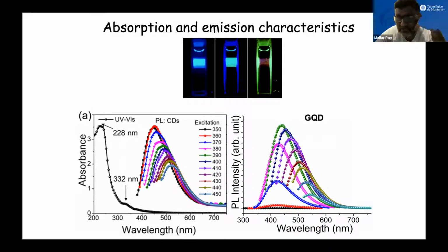Now, this kind of feature was very well known for the graphene dots. And in fact, it's difficult to make graphene dots, small pieces of graphene in a colloidal suspension. To our amazement, when we compared the optical properties of the graphene quantum dots and the amorphous quantum dots, we saw a striking similarity between them. These graphene quantum dots, which are much more difficult to make, more exotic, and these amorphous clusters of carbon dots, their photoluminescent emission spectrum, their UV visible absorption spectrum, their photoluminescence excitation spectrum, their quantum yields, they're almost comparable.